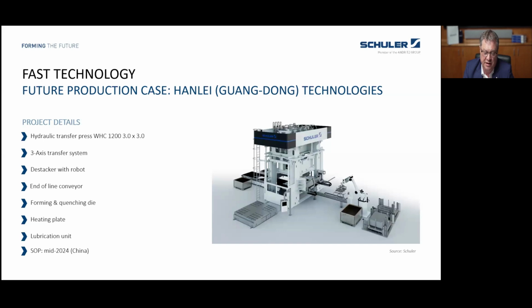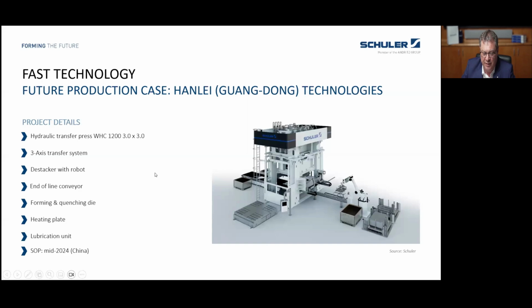The drive of the press is a classical hot stamping press drive, servo controlled and extremely fast for the forming of the part. Then we use a triax transfer system and the classical destacker with a robot and a marking station, the end of line conveyor, and we also have the forming and quenching die, which has the heating plate and a lubrication unit. And this line will go in operation mid of this year in Guangdong in China, which is south close to Hong Kong.